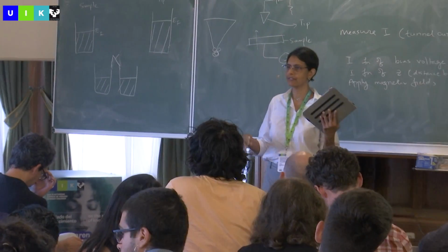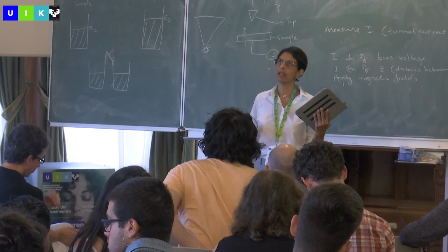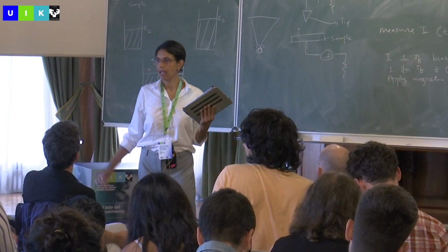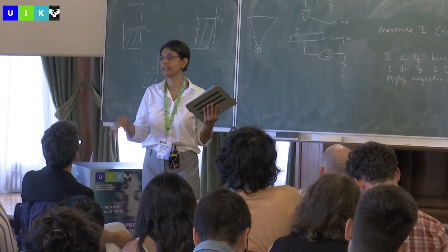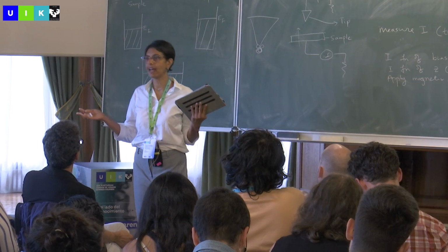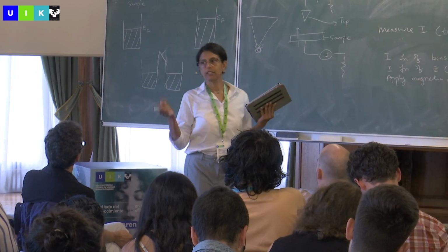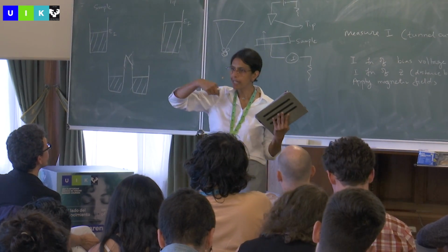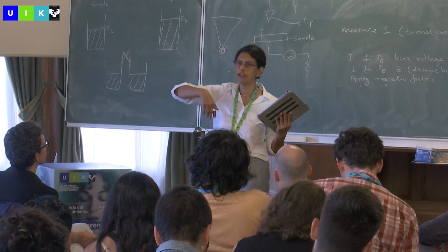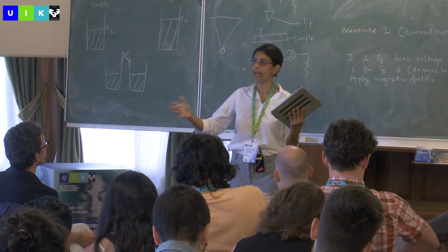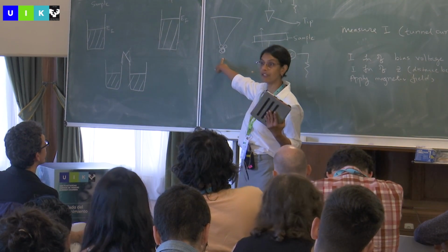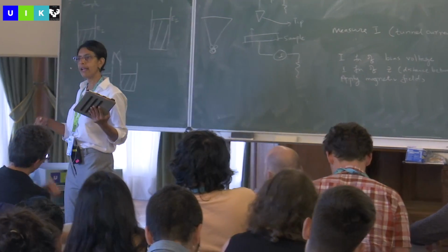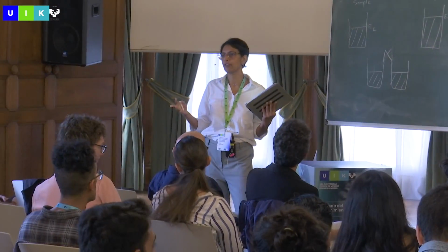That it's a flat density of states, yeah. So what we do is we can prepare the tip on another metal, which also has a flat density of states, like copper or gold. We know these have flat density of states across the Fermi energy. You take this tip that you'd like to use, you go on this metal, and make sure that the tip density of states is flat. If it's not, you can play games: you can apply an electric field, things will drop off the end, you can poke the metal if you want. You just make sure that the tip density of states is flat before you use it.